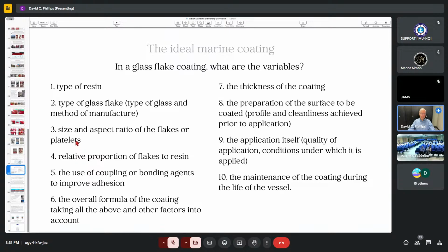I prefer to call them platelets because flakes can easily be much too small. The relative proportion of the flakes to the resin. There needs to be enough glass in there to make it effective. The use of coupling or bonding agents to improve adhesion, very important. Internal adhesion within the coating, but also adhesion of the coating to the substrate, like the steel. So then you have the overall formula of the coating, taking all of these factors into account: type of resin, type of glass flake, size, proportion, and bonding agents.